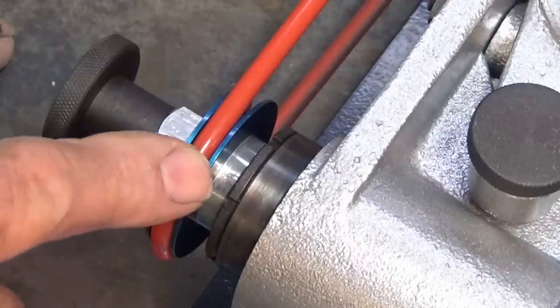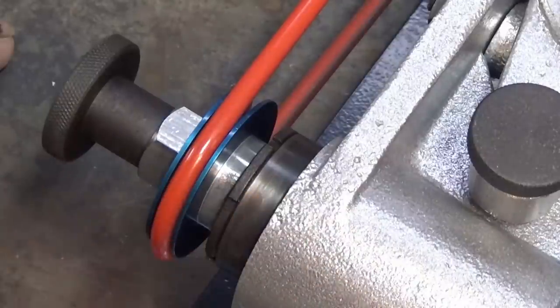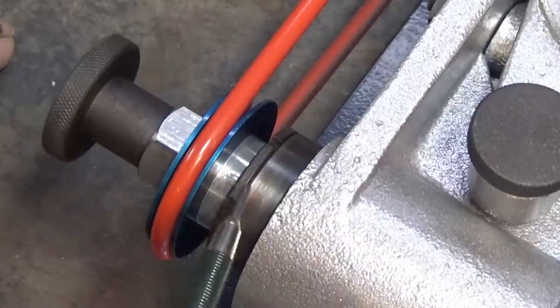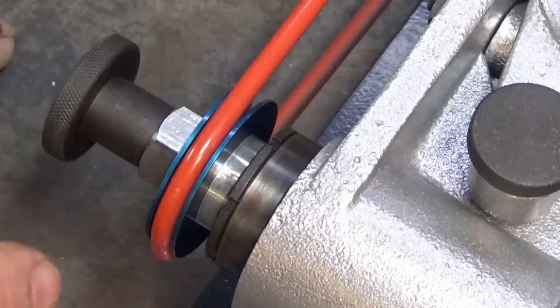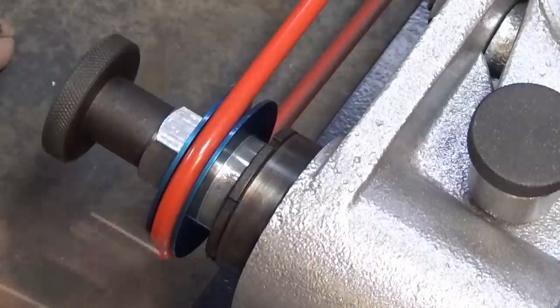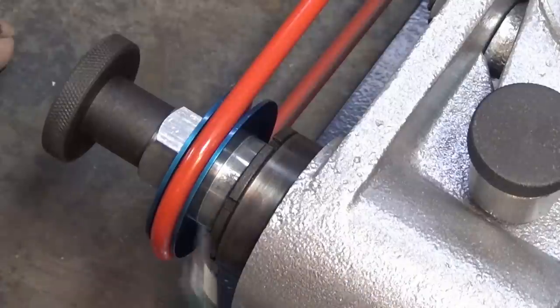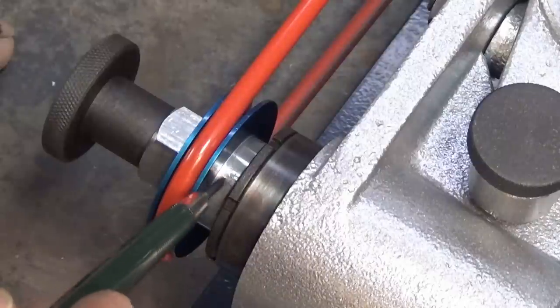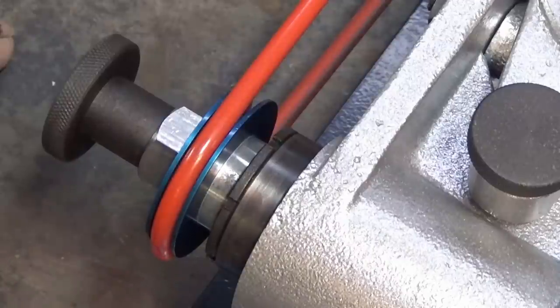Now, the pulley itself is a little bit complicated because there are labyrinth seals on both ends of the spindle. And that means that this collar has to have an annular groove in the face. And that means trepanning out that groove, and I must have got lazy and just decided to actually make that part separately and then stick it on with Loctite. And what's happened is that that collar is completely electrically isolated from the rest of the part. And in anodizing, if it doesn't conduct electricity, it doesn't anodize.